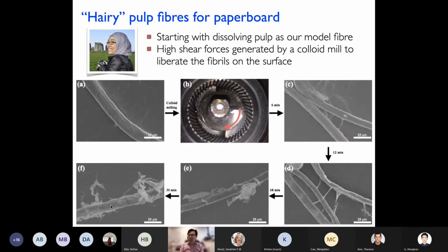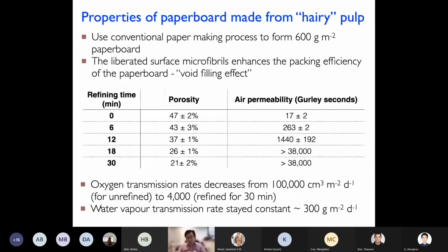So we call these fibers hairy fibers for now. We don't go all the way through in the context of refinement to isolate the individual 50 nanometer fibers. We just let the 50 nanometers stay attached to the micrometer-sized fibers. We create paperboard out of it, in this case 600 grams per square meter paperboard. What we observed was that with increasing refining time, we actually reduce the porosity of the final paperboard, and that leads to an increase in the time required for a volume of air to pass through.